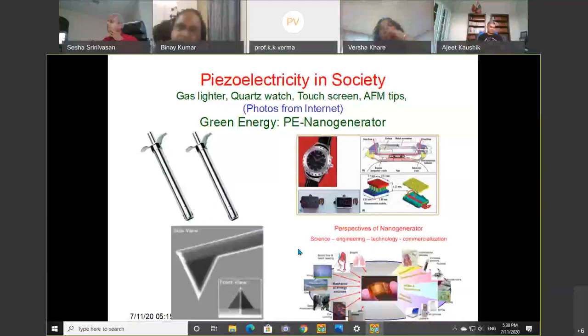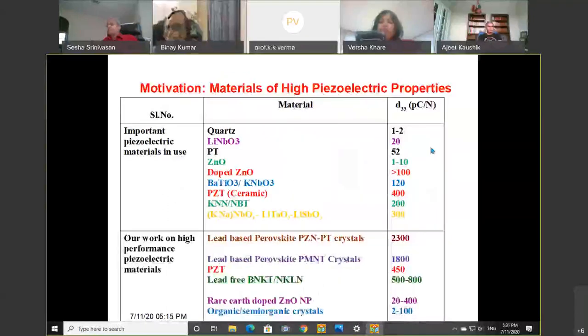Different materials are used for making this piezoelectric device. Just to give you one comparison, I have explained what is d33, that is how much charge can be developed with a particular force, 1 Newton force. So quartz is the most common name, but it has a very small value, 1 to 2. Lithium niobate is 20. ZnO, when it is pure, is 1 to 10. Of course, we have achieved up to 300 to 400 with various types of doping. PZT is a material which is very much in use by industry and so many other technological applications, and it has a value of nearly 400.